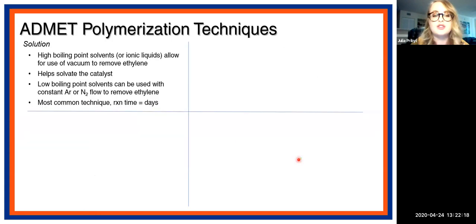Which brings me now to the different polymerization techniques that we use. So first, and by far the most common technique, is to perform the ADMET polymerization in solution. So you can use high boiling point solvents or ionic liquids, which are nice because those substances allow us to apply vacuum to remove the ethylene, which, if you remember back to the ADMET polymerization mechanism, removal of ethylene is essential to drive the polymerization in the forward direction towards high molecular weight polymer. It also helps to solvate the catalyst.